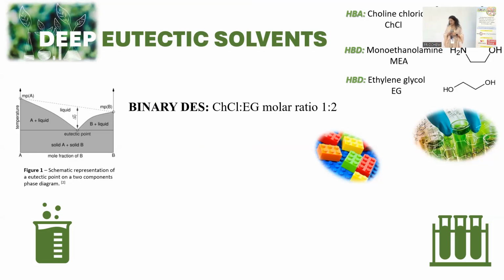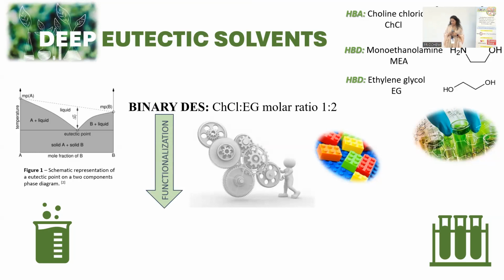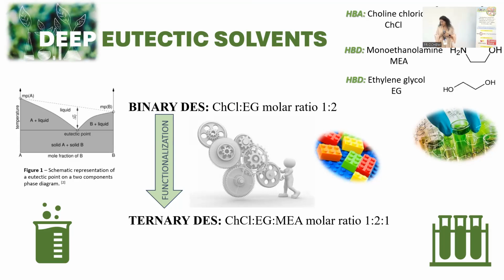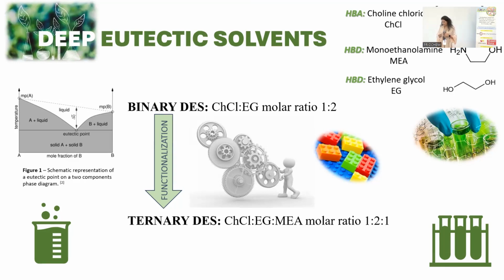The solvents can be categorized by their number of components. The binary solvent from which we started was made from choline chloride and ethylene glycol. But our study didn't help us. The results on CO2 capture weren't so attractive. Therefore, we functionalized it by adding another component, monoethanolamine, which is very well known for its affinity for CO2 capture.